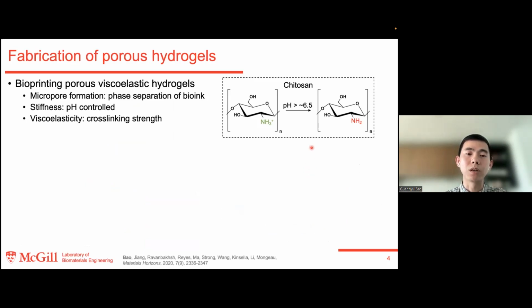We have used a biopolymer called chitosan to achieve this goal. Chitosan is a polysaccharide that can be derived from nature, such as the shell of the shrimp, the crab, or even the mushroom, such as the cell wall from the fungi. Chitosan has primary amine groups, and when it is exposed to solutions with a pH lower than 6.5, these primary amine groups are positively charged. When the pH of the solution changes above this value, the primary amine groups deprotonate and become neutral, which allows the chitosan to form hydrogen bonding within the chains themselves, which enables the self-cross-linking mechanism.